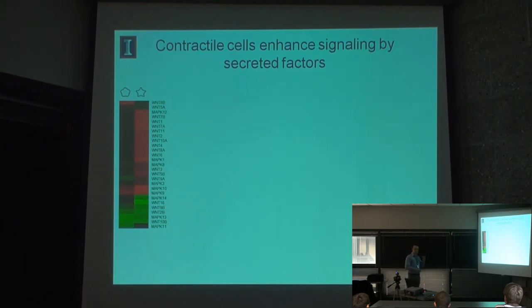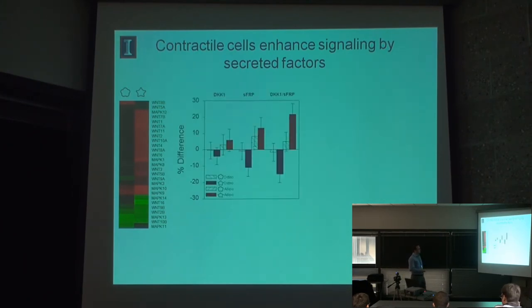So we wanted to try to figure out if we can get a direct link to gene expression. And so we inhibited Wnt extracellularly using just small protein molecules that inhibit Wnt signaling. So DKK1, which inhibits the canonical Wnts at the membrane. And when we add DKK1, we see a slight increase in adipogenesis and decrease in osteogenesis. Not very significant, though. When we add a secreted frizzled-related protein, which will block all Wnts in solution as well as at the membrane, we see a bigger increase in adipogenesis. And then when we mix those two, we pretty much lose all of our shape-directed differentiation, suggesting that with this contractility, the Wnts are really playing a serious role.